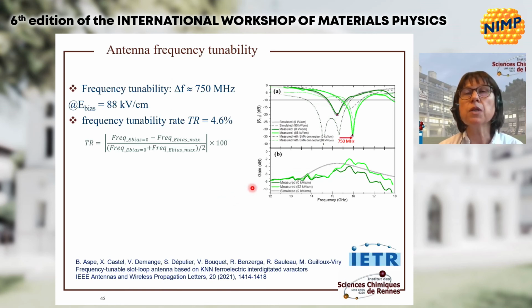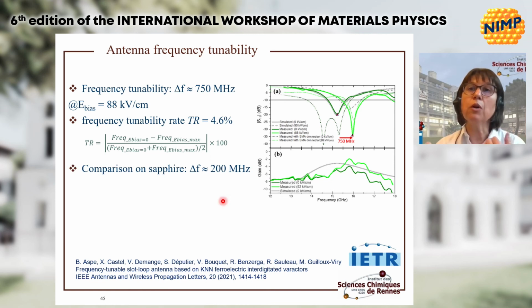And a tunability of 750 megahertz has been observed. That means 4.6% for this antenna on magnesium oxide substrate. This value of tunability is equivalent to the one reported for the same type of antenna with the same size with other materials like BST. That is the state of the art today. So it's comparable. In comparison, on sapphire substrate, with a less epitaxial growth and lower quality, we have a lower tunability of this frequency.